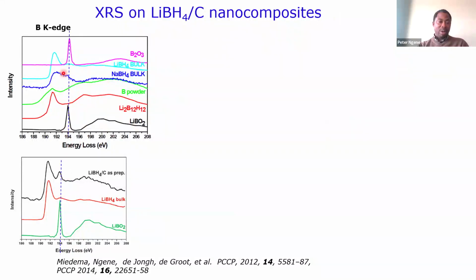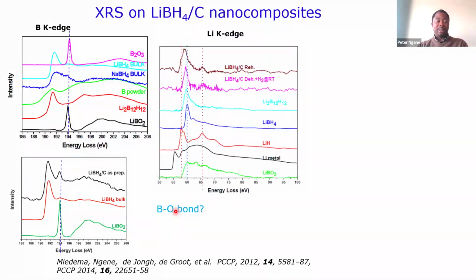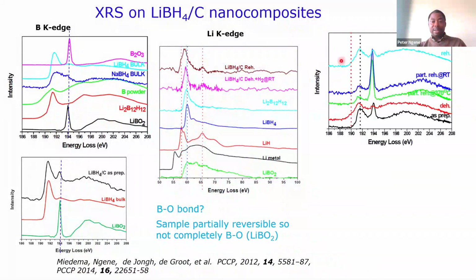And if we look at all these things, we do see that actually our peak, which appears in this material, is more of the oxidic boron peak. So you can see here B2O3 or also LiBO2. And the conclusion at that time is that we have some kind of boron-oxygen-like bond, which means that maybe our samples are decomposing. So also we look at the lithium K edge, not very good data, but the summary of this is that we thought, okay, that we have this B-O bond. So the sample has oxidized, even though we try as much as possible to prevent oxidation.